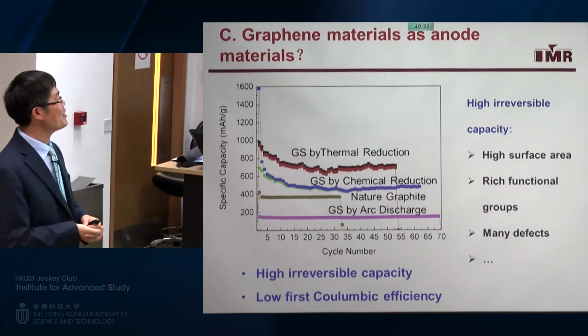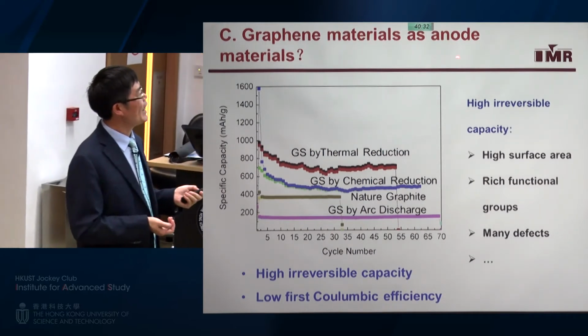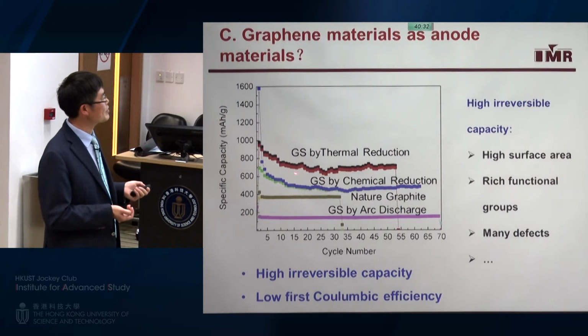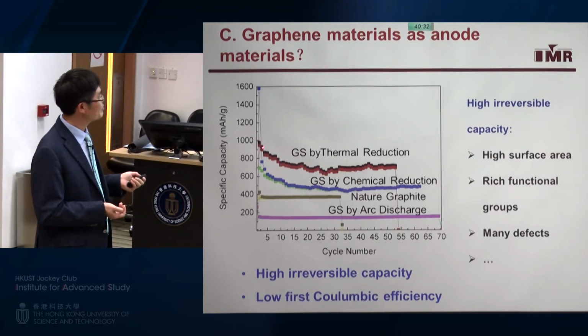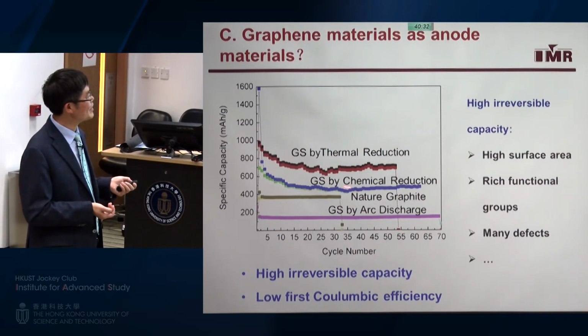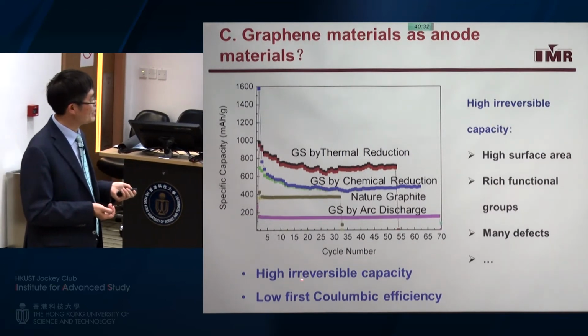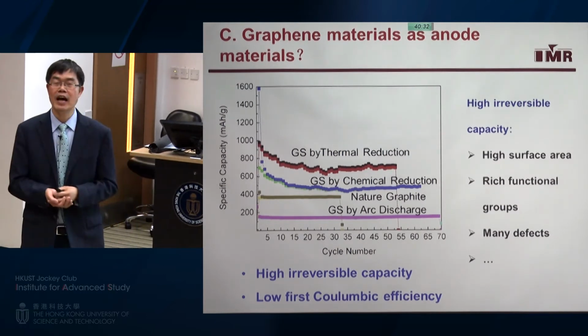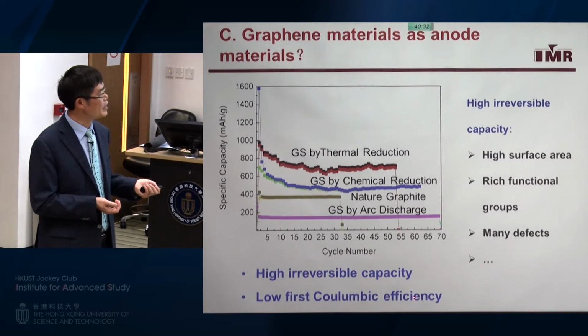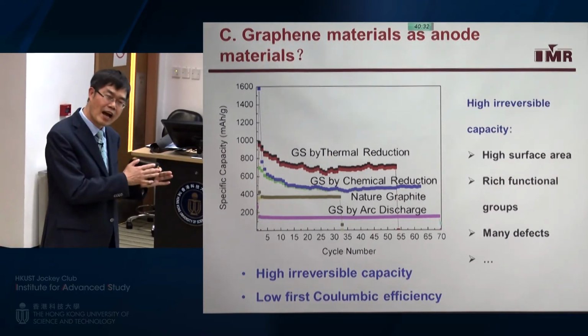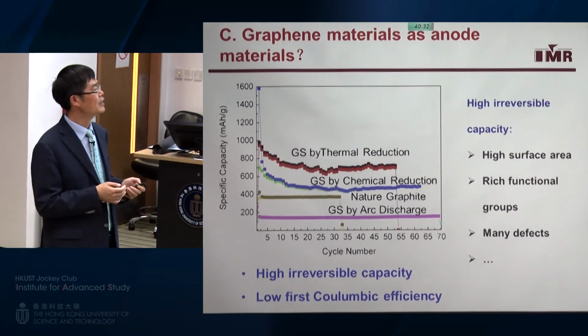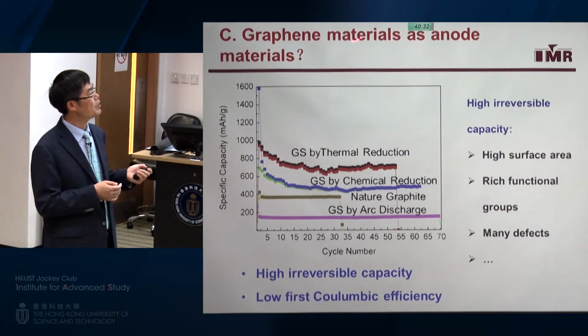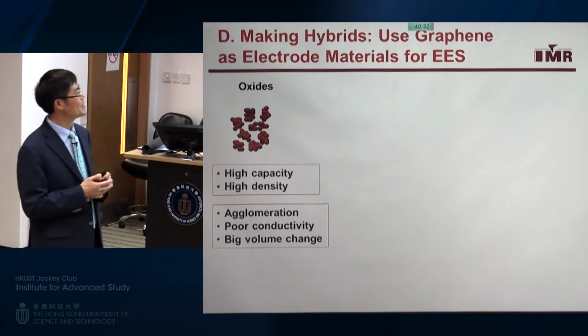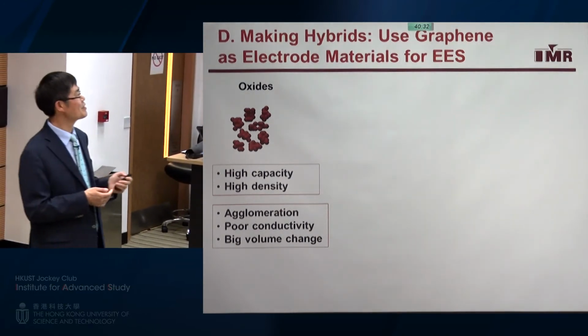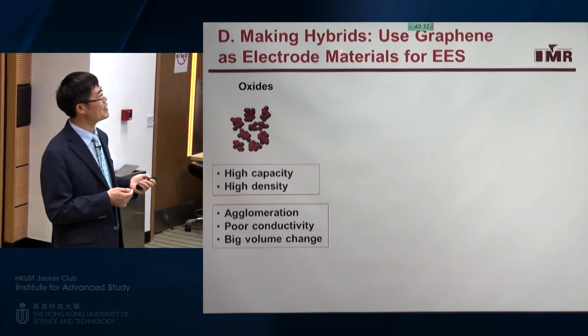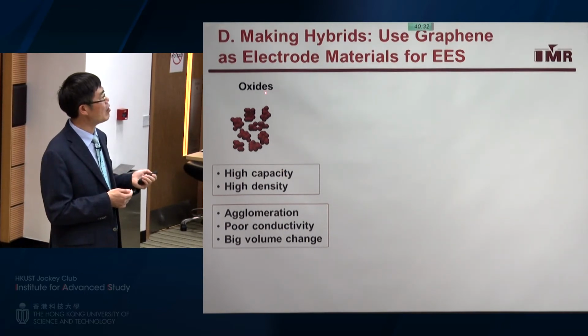Some people also ask me, can we use graphene material as anode material? We have also tried this research many years ago, but we found that although the capacity is very high, the drop is also big, which means the irreversible capacity is very high as well. That also means very low Coulombic efficiency. So although we can have high capacity, it's not practical. So I will say we cannot use pure graphene material as anode material. But it is a very good matrix for making a hybrid or a composite with other high capacity materials such as oxides.